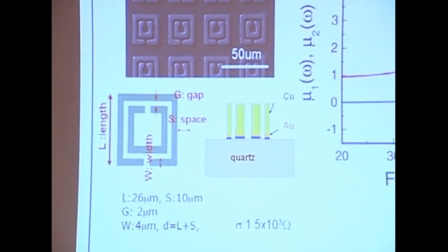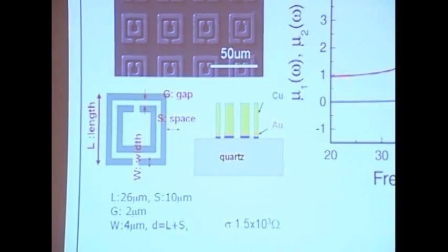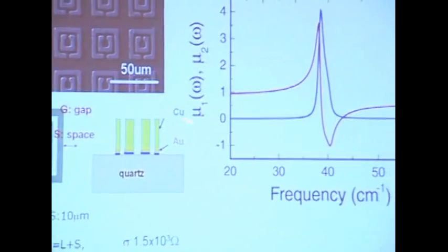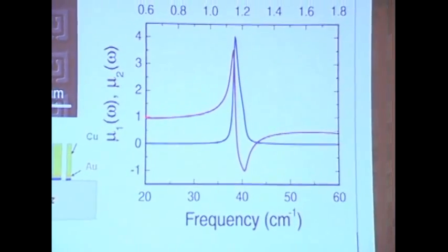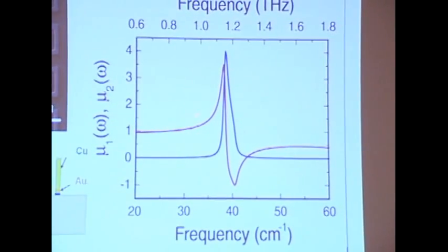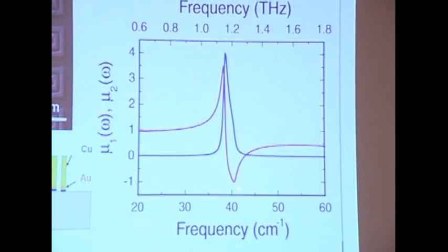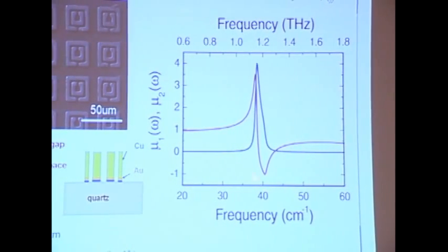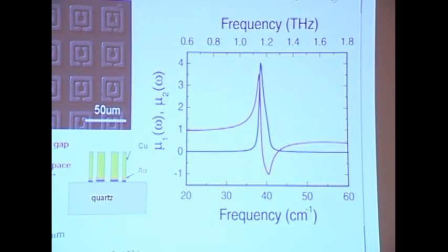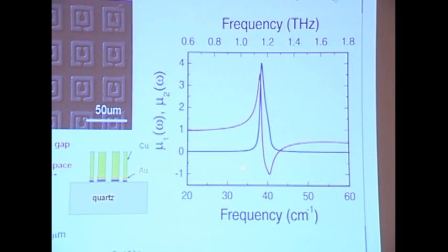This is our analytical calculation that shows the real part of the magnetic permeability mu. It shows that indeed it can go beyond 1 or below 0, so it could have a negative value as well. And this clearly is a resonance-based phenomenon. As with many resonance-based phenomena, you have a very large loss associated with that as well.